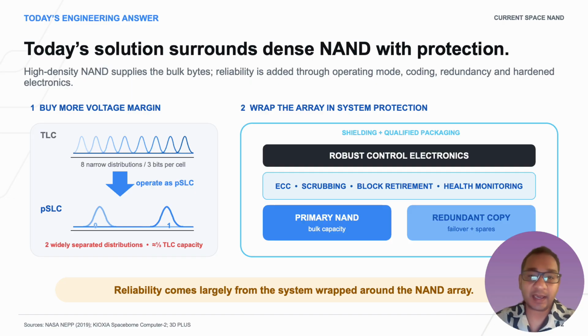TLC can be operated as a pseudo SLC, using only 2 widely separated threshold states instead of 8. Because TLC normally stores 3 bits per cell and pseudo SLC stores only 1, the raw capacity penalty is approximately threefold. Systems then add error correcting codes, scrubbing, block retirement, redundancy, shielding, monitoring, and robust controllers. These methods are effective, but they shift reliability into overhead around the array. The dense NAND still stores charge, so protection reduces risk rather than removing the underlying radiation interaction.